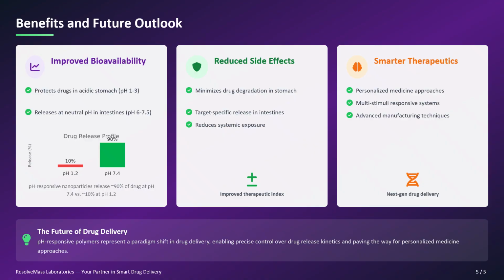When done right, pH-responsive polymers offer a remarkable set of advantages. They shield sensitive APIs from stomach acid. They enable site-specific drug release in the intestine. And they drastically reduce systemic side effects by preventing premature exposure. In controlled studies, such polymers have shown 90% release efficiency at pH 7.4, compared to only 10% at pH 1.2. A clear demonstration of their precision.